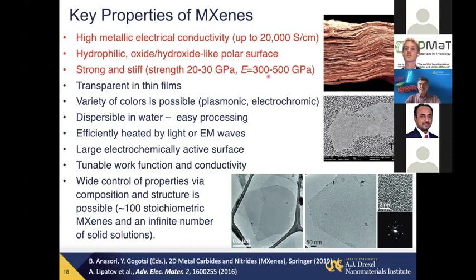They inherited their mechanical properties from strong lattices of cubic transition metal carbides. For example, bulk titanium carbide is widely used for cutting tools, just like tungsten carbide. You can look at a layer of MXene, and you can see a single flake on an aluminum oxide substrate, probably about 20 micron in size, and a few flakes on a TEM grid. You can look at them as a 1-1-1 cut of the cubic sodium chloride lattice of conventional transition metal carbides or nitrides, like titanium carbide, titanium nitride, TiC, TiN.